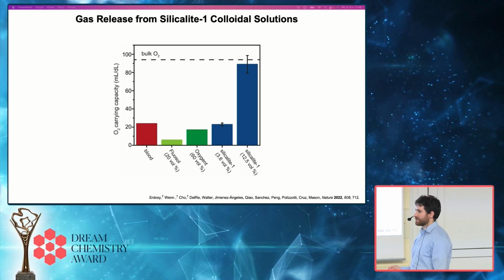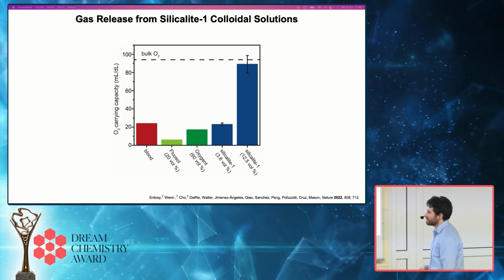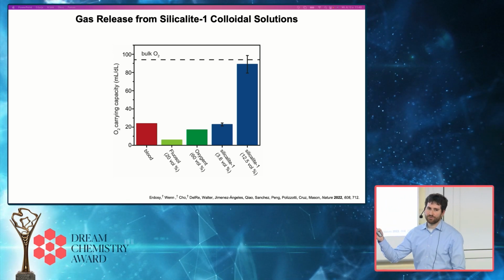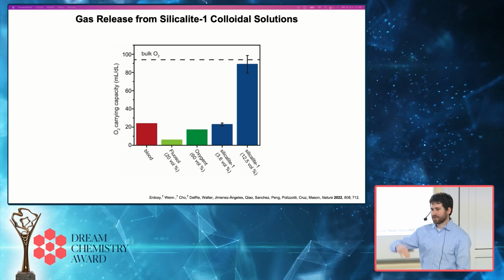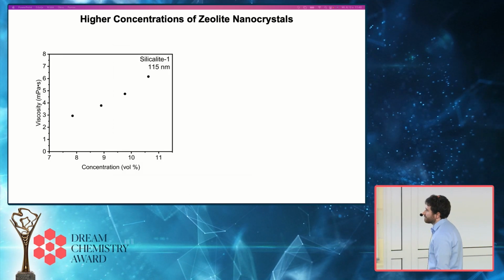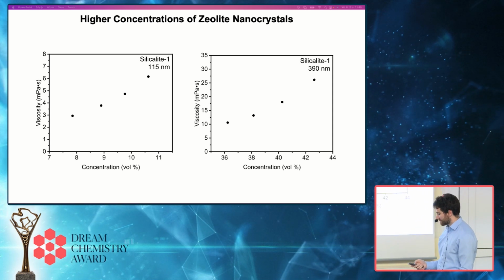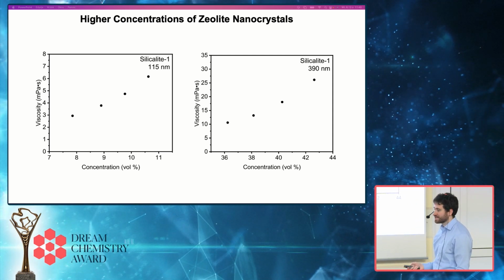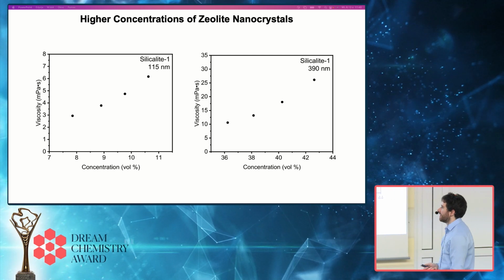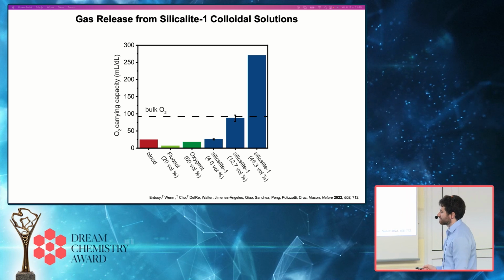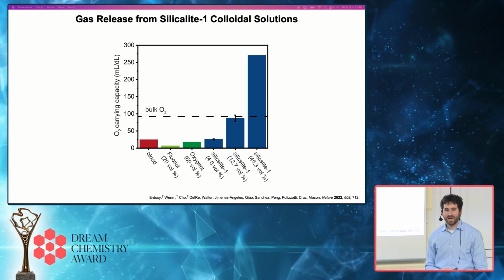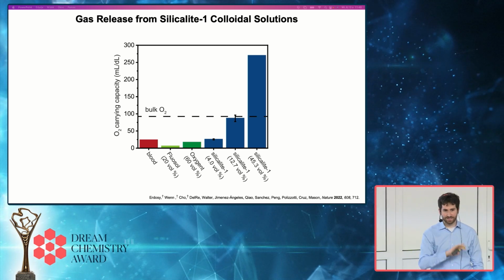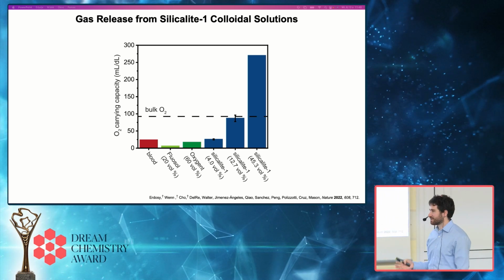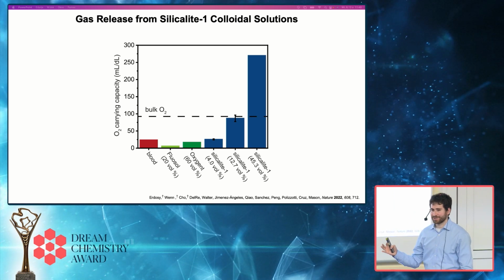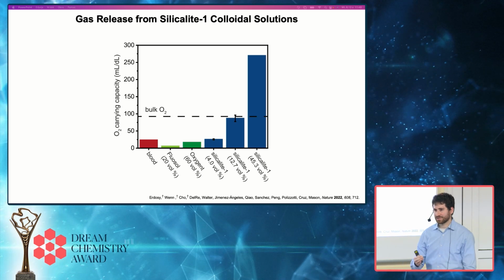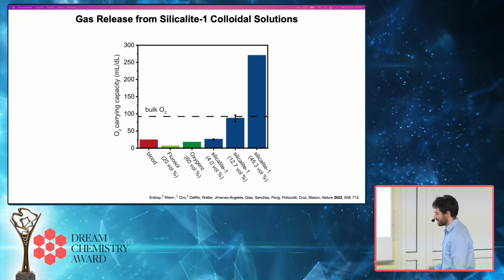If we go to higher concentrations of these zeolite nanoparticles, then we can match the bulk gas oxygen density in water. So you have the same overall density of oxygen in your aqueous solution as you do in the gas phase above it. If you play with particle size, you can get to quite high concentrations of solutions at relatively moderate viscosities, so viscosities that are comparable to those of blood. And you can reach much higher concentrations of solutions. So I think we're up to about 50 volume percent now, and you can get oxygen carrying capacities that far exceed the gas density. So this got us excited about using these aqueous solutions for a variety of different applications where one is really limited by how much gas you're able to transfer through water, both in biomedical applications and energy applications.